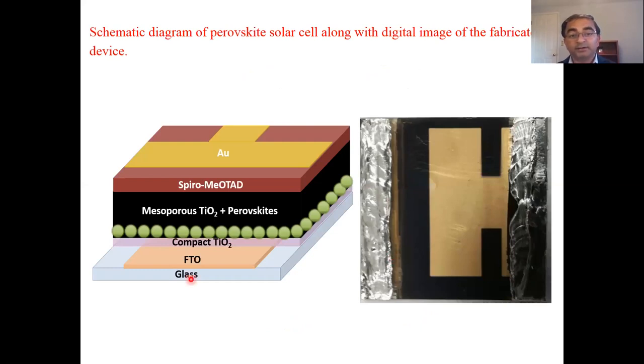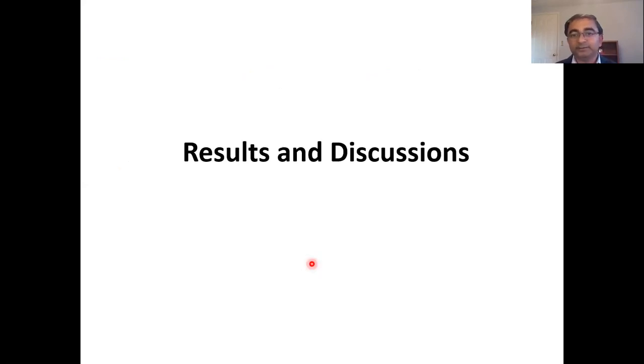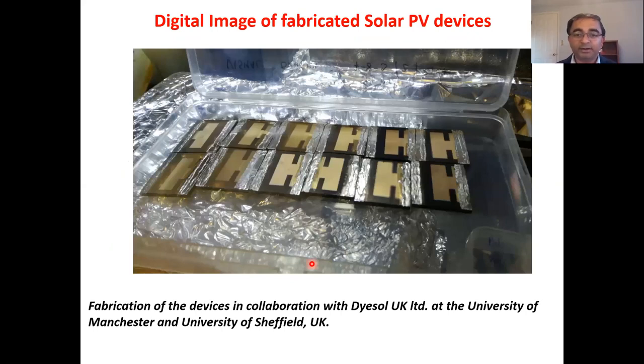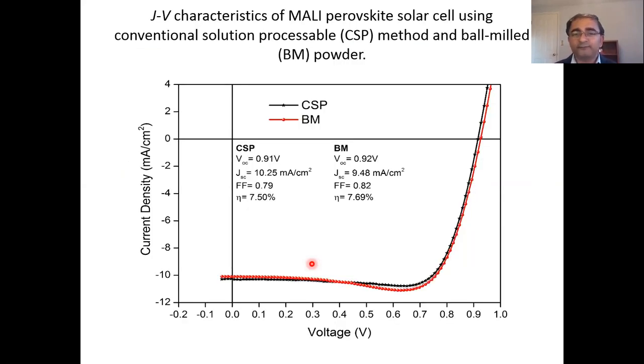And this is the block diagram, the structural diagram of that solar cell. We used glass, FTO, compact TiO2, then mesoporous perovskite, the spiro for the hole transport layer, and then gold. And this is the batch of solar cells which I have fabricated in the UK. And there are some IV characteristics which I have found.